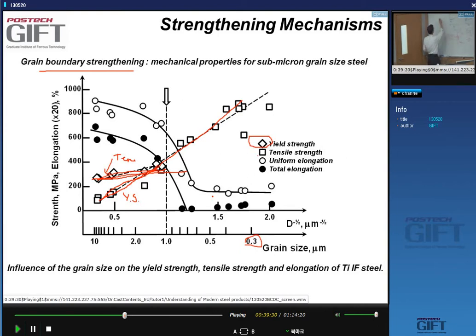When that happens, if I make a plot of stress and strain, the yield strength and the tensile strength are here. If the yield strength comes next to the tensile strength, there is no elongation anymore. The material just yields and necks and breaks. And this happens at around 1 micron in grain size. So you cannot limitlessly reduce the grain size. At one point, it becomes pointless because you destroy the ability of the material to plastically deform.